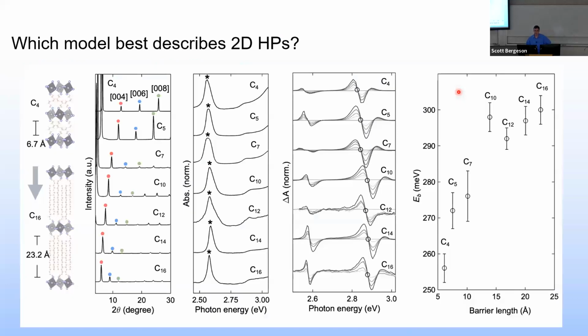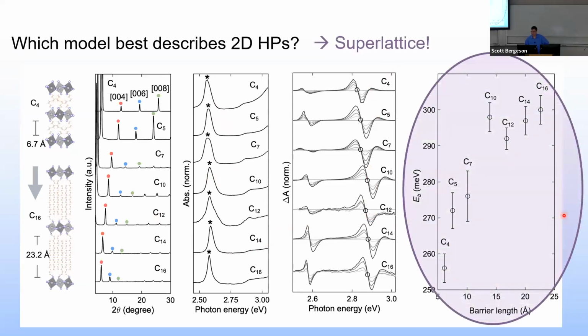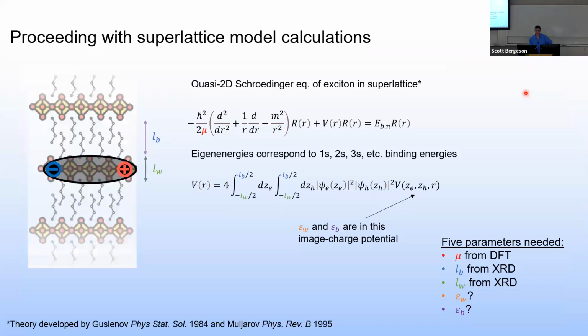And so one of the things we did was to produce a series of perovskite materials that had different lengths of organic molecules, ranging from pretty short to pretty long. And then we did our electroabsorption measurement, and this is the result of the binding energy versus the barrier length. So there is a clear dependence between the two. And again, this was something that basically had not been seen before. There was one really old report that nobody followed up on. And so this is very good evidence that the superlattice model, so communication between layers, is what we needed to use.